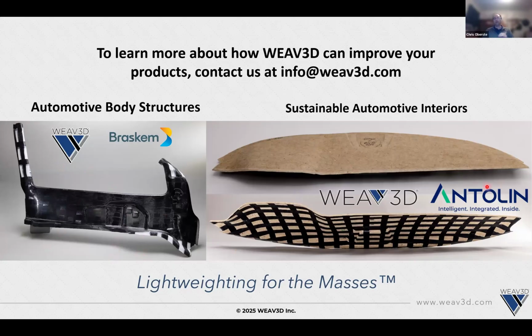With something like the natural fiber nonwoven mats, the fiber content and the fiber length is high enough that even though the lattice is only on one side, the actual total volume fraction of lattice in this part is still relatively small. The natural fiber nonwoven is able to balance out the warpage the lattice induces, which you would normally see in an asymmetrical laminate. It's not going to be 100%, so you do have to design that in, but it is something that we can simulate in many of these components. If we know what the CTE of the material is, we can calculate how much warpage that part needs to compensate for in the tooling.